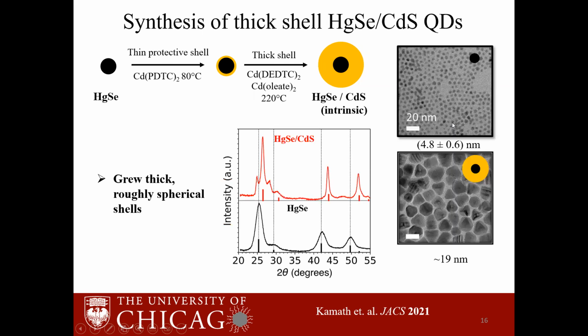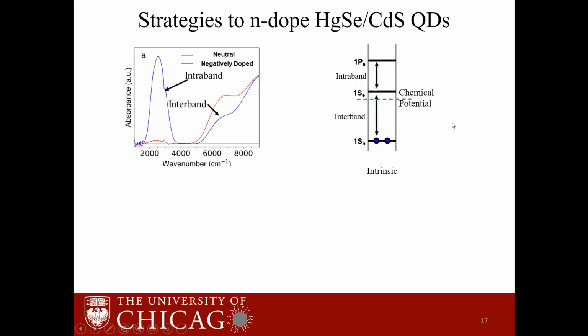And using this method, we were able to grow a thick and roughly spherical shell up to a final size of around 19 nanometers. And the XRD spectra show that the crystal structure of the shell grows mainly along the crystal structure of the core, which is a zinc blende crystal structure. So now that we have the synthesis, we have a second step that we need to do before we can measure the quantum yields. As we saw before, we need to dope the quantum dots for us to observe these intraband transitions. Right after synthesis, the quantum dots are intrinsic and they don't have electrons in the conduction band. So we need to find a way to put electrons into the conduction band for us to observe this intraband transition at 2000 wave numbers.